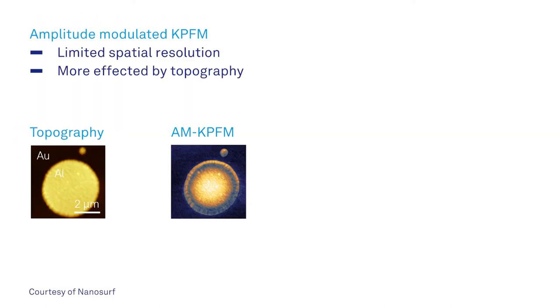There is one caveat to AM-KPFM though. The large stray capacitance from the tip and cantilever geometry can limit the spatial resolution. But there is a great alternative, KPFM methods based on frequency modulation.